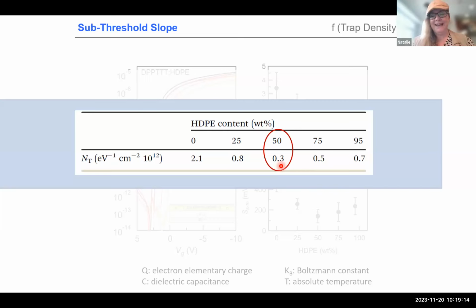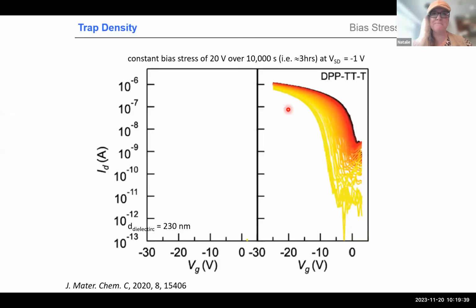semiconductor reduces traps. It's a bit paradoxical because for those who come from the bulk commodity world, polyethylene is actually not, for instance, a good oxygen barrier. But we believe it helps because polyethylene is obviously very hydrophobic. So it will repulse water and moisture, and that seems already to be big enough to help reduce traps. And other evidence is found for that.